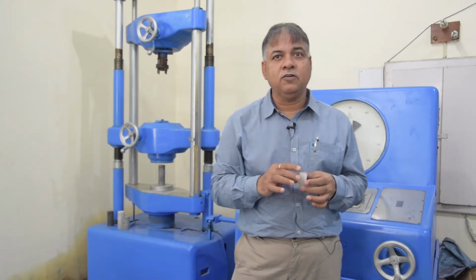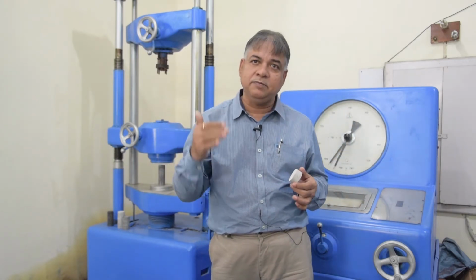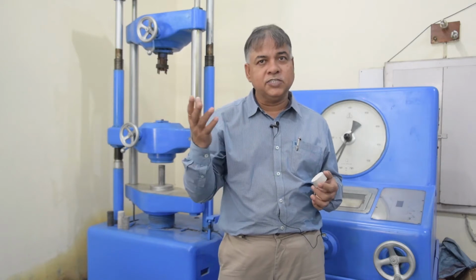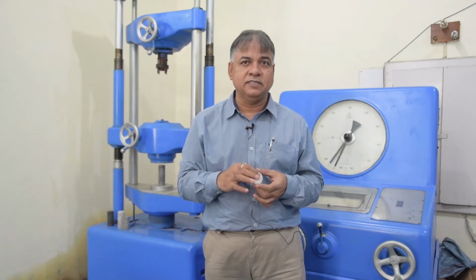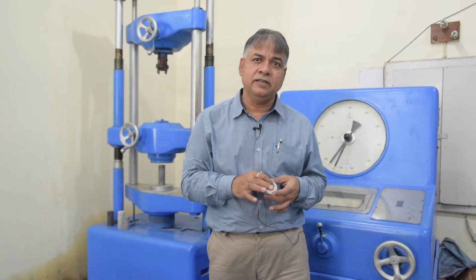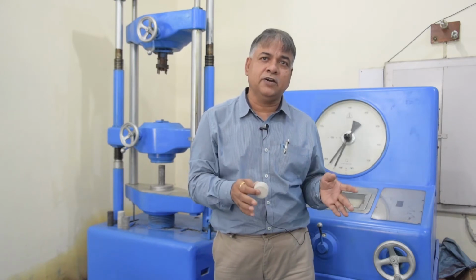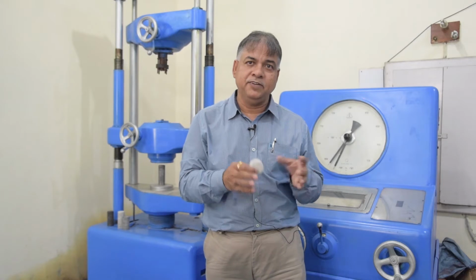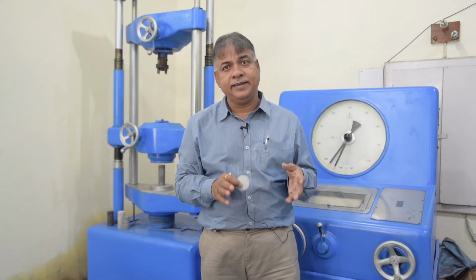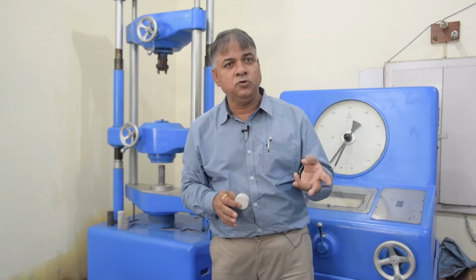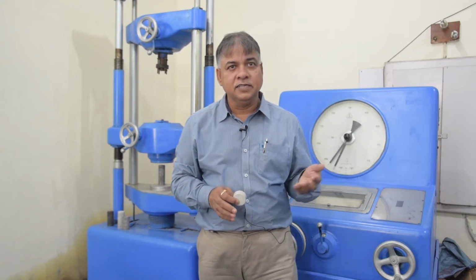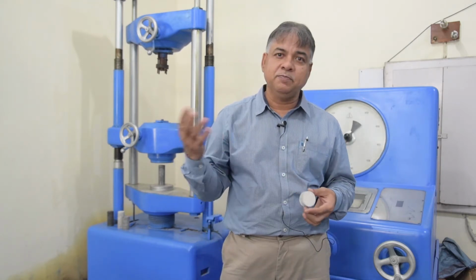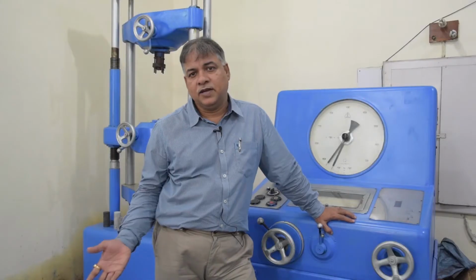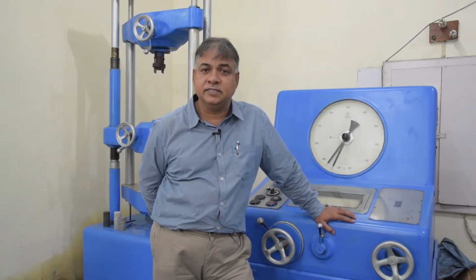This property, or variation in this sigma c by sigma t, the ratio of compressive strength to tensile strength, becomes very, very significant whenever you are going to break the rock through blasting, and we term it the blastability index. Just by knowing the two values, compressive strength and tensile strength, and putting them in a ratio, you can understand how the rock is going to break if you are deploying blasting as a tool for breakage of rock. I have already shown you how compressive strength is determined.